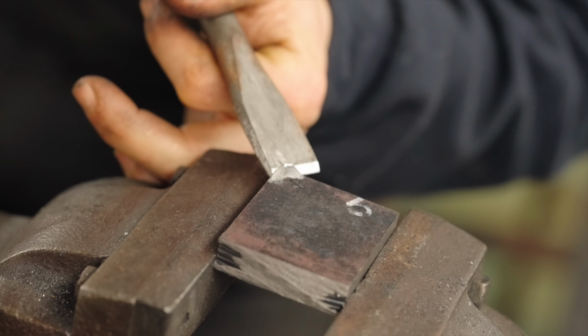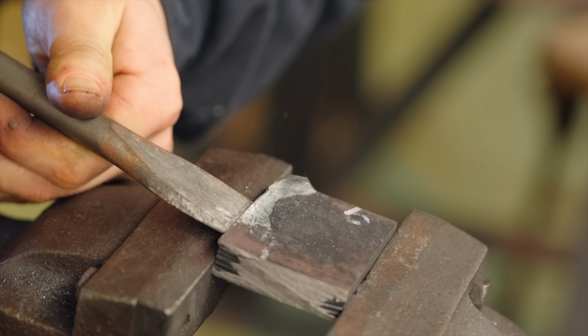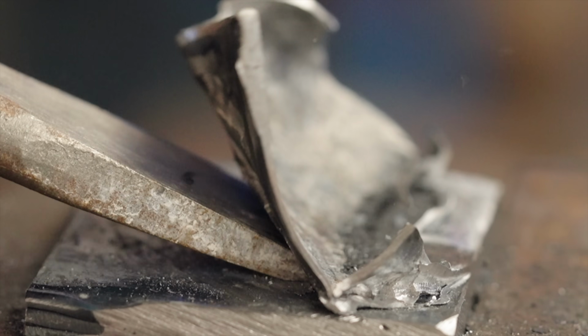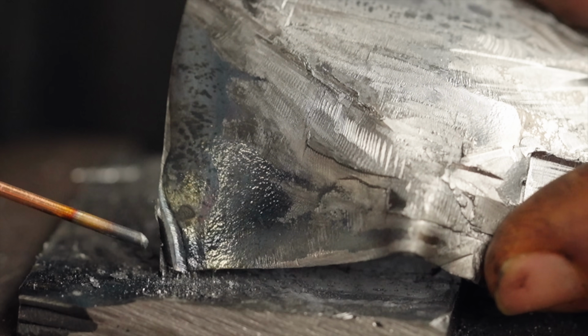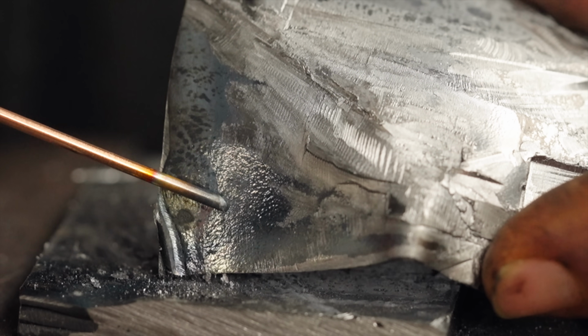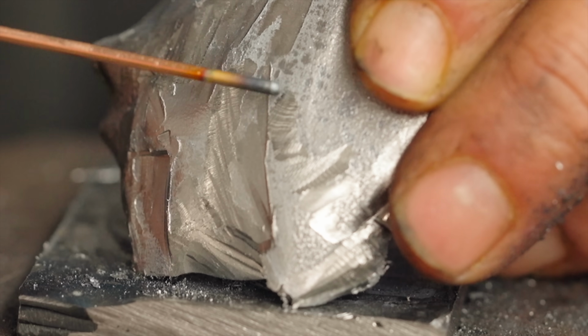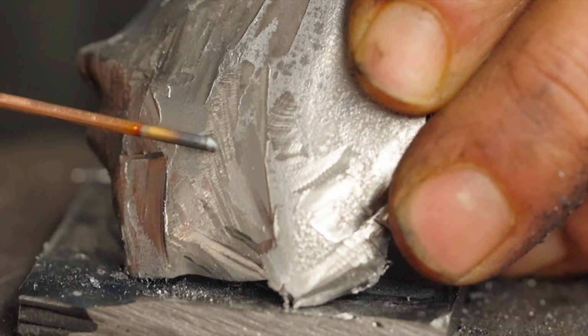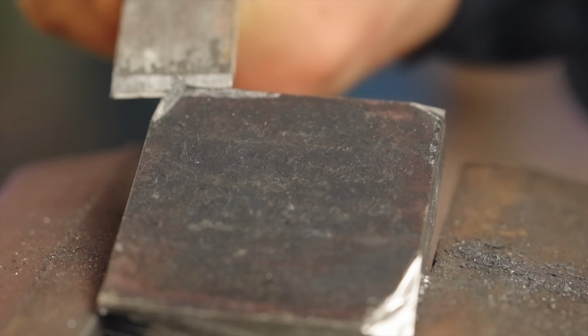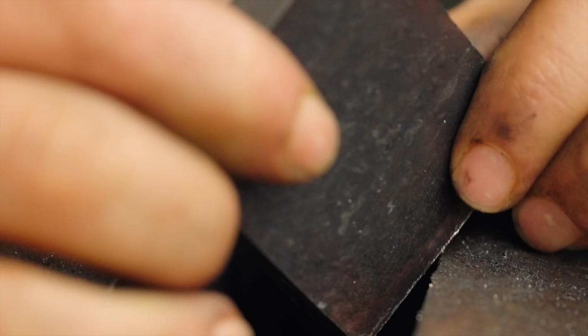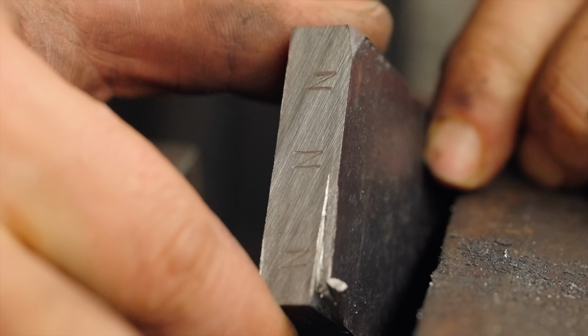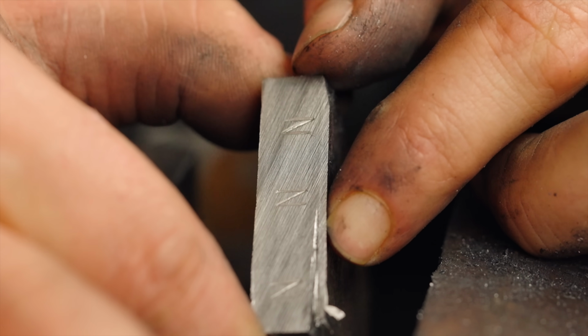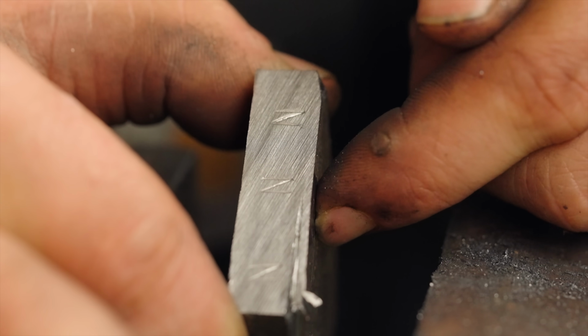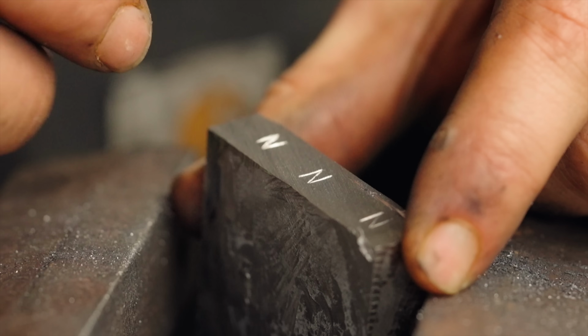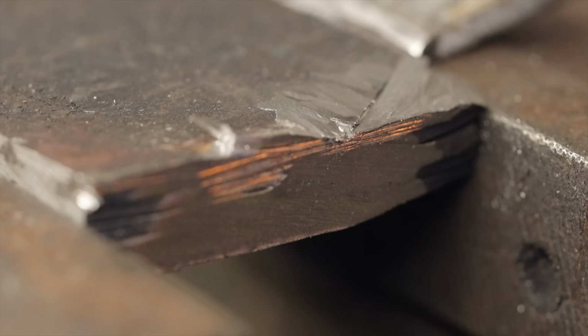Oh my goodness, we are peeling it off. Yeah, look at that. That is so fascinating. You can see the discoloration here at the joint interface where that unclean oxidized box hasn't properly bonded there. The areas that were much harder to peel off did not have that same discoloration. The backside is not peeling at all, and that just tells you how close the margins of success and failure can be. One side of this billet, the jacket bonded really nicely. The other side of the billet, it did not.